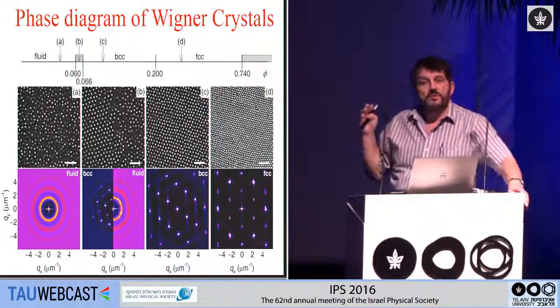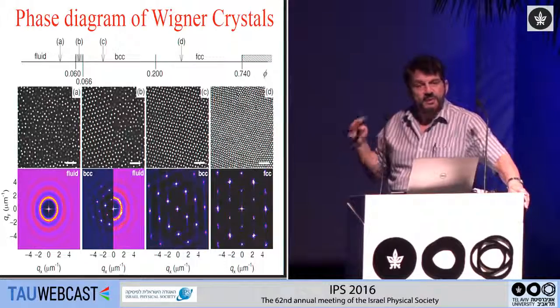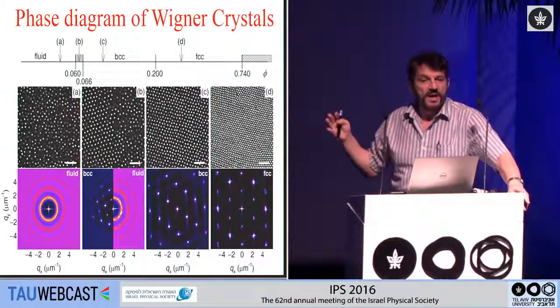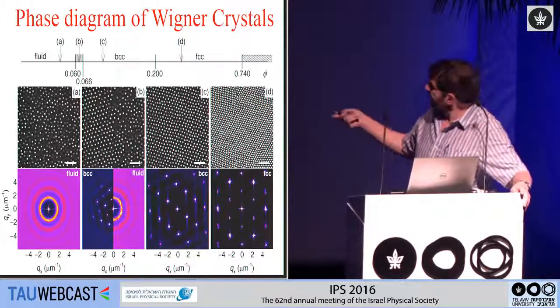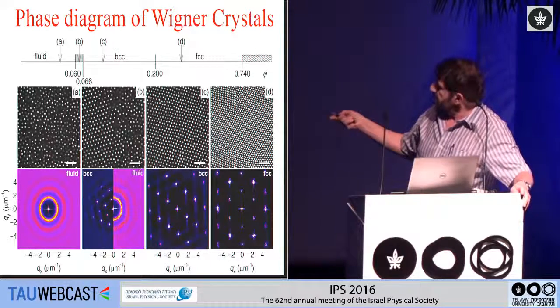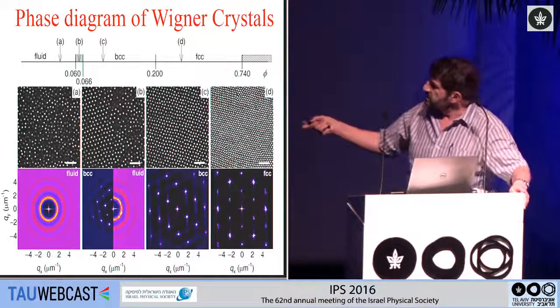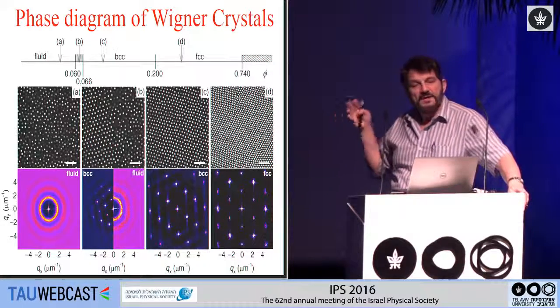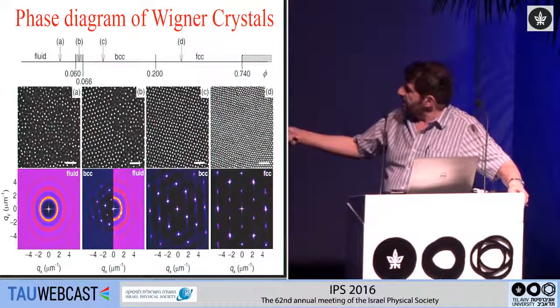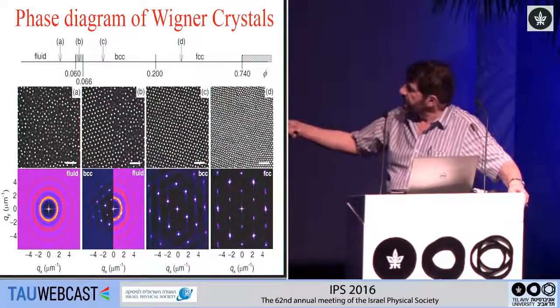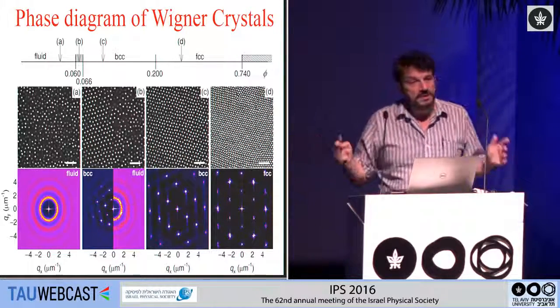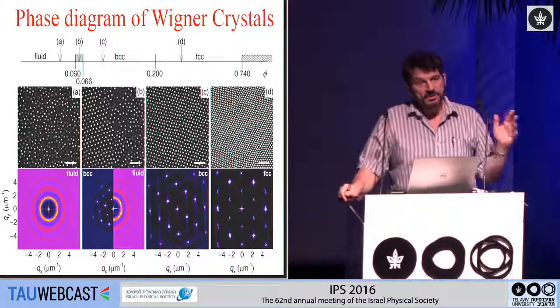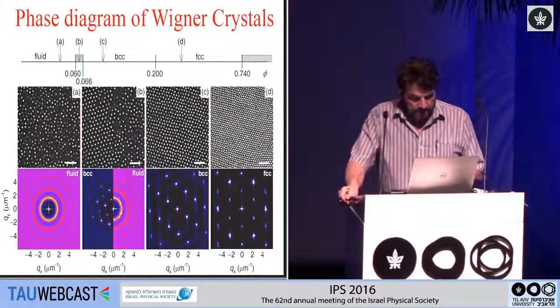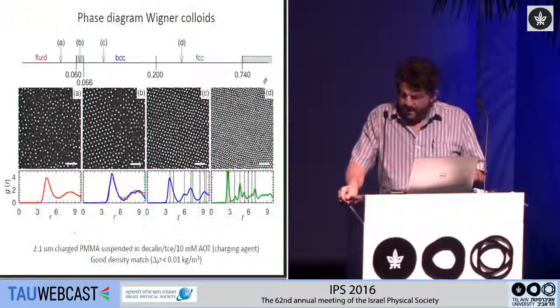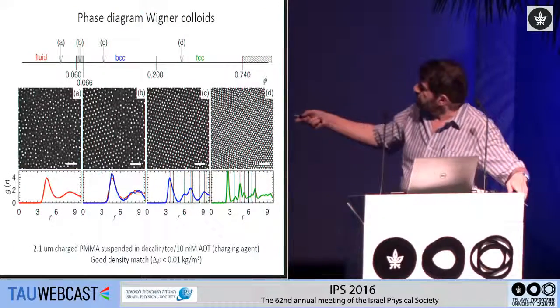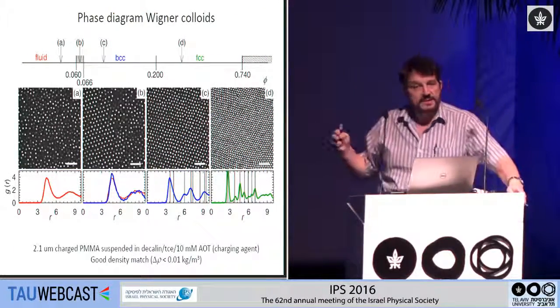You can also do the more traditional thing, that is do scattering. You just take the images and Fourier transform them to find the scattering. And you can see the FCC and BCC scattering. In the coexistence, you can do it from both the liquid and the crystal region, and you can see part of it's BCC, the other part is fluid. Of course, in the fluid region, you no longer see the peaks in the Fourier transform. You no longer see the scattering of a crystal, but rather it's a liquid. And you can average the g(r)'s, and you can see exactly the same kind of behavior.